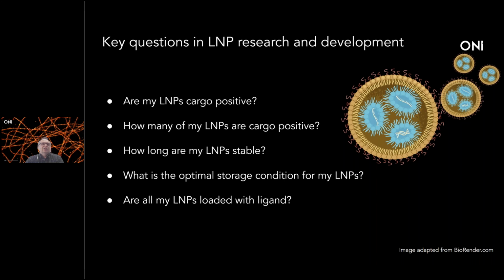There are multiple different storage conditions for these lipid nanoparticles, but which one is the right one? Most lipid nanoparticles are stored with some sucrose, which could be 8, 10, or 15% of your solution. However, whether that is the right storage condition is still unknown.